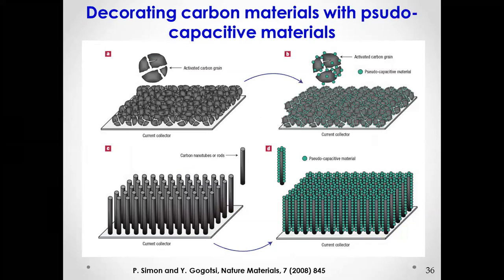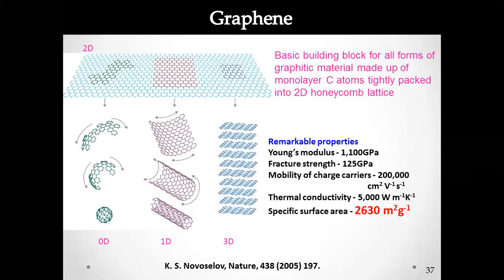For example, here this is activated carbon, and these small particles are called pseudo-capacitive materials. It may be some polymers, it may be some metal oxides. These can be combined. This was done maybe several years before, maybe a decade before. Instead of activated carbon, they are using some carbon nanotubes. They decorated them with some pseudo-capacitive materials, and then they have used it for supercapacitor application. Recently, graphene came into the R&D, which has very high surface area. More importantly, the conductivity of graphene is much higher than any metal. Since the conductivity of the material is very high, and it has a very high surface area of 2630 meters squared per gram, this may be the best material for supercapacitor application.